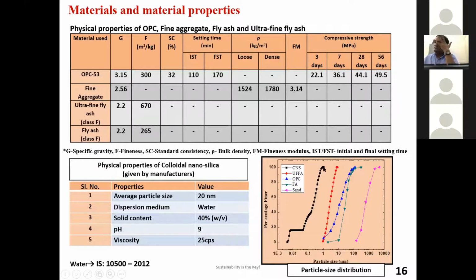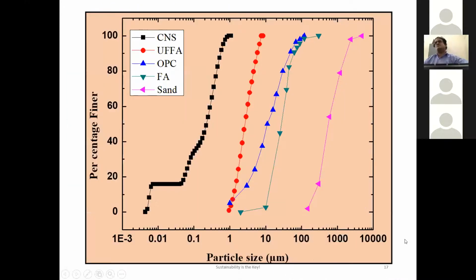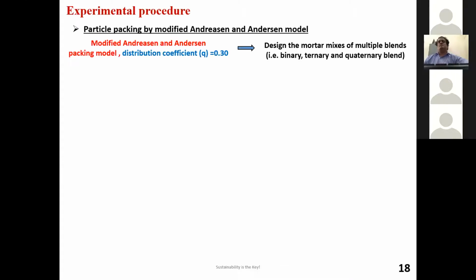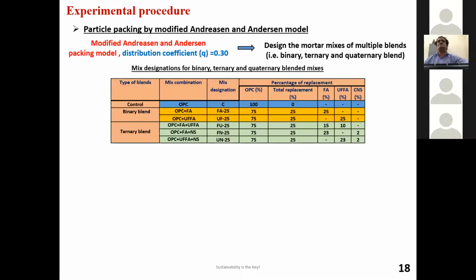Now you can see here, this is my particle size distribution curve for all the materials. This is my colloidal nanosilica, and this one is my sand, and these are the particles in between. You can see this ultrafine fly ash, almost single grain, from almost 1 micrometer going up to 5 micrometer. Similarly, this is my OPC and this is my fly ash. This is the same thing, an extended version again.